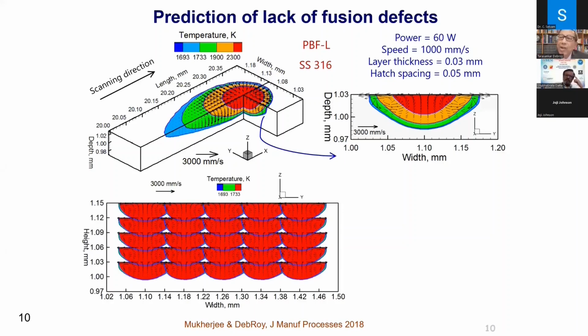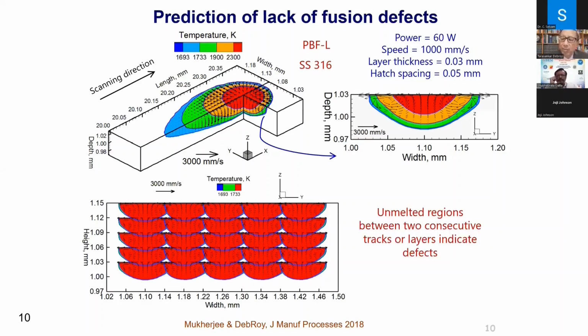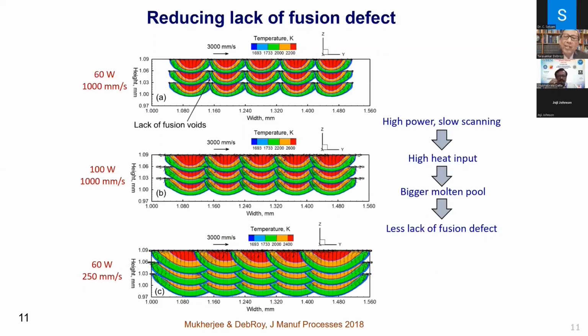So these watermelons can be put one after the other so that you can see how they are being deposited, and the most important thing is that you see holes in them. These are lack of fusion defects. They have not had sufficient overlap between layers and between adjacent hatches. So we need to modify that, and we can do so for different process variables.